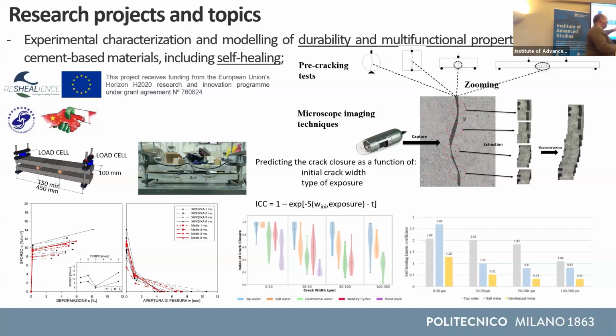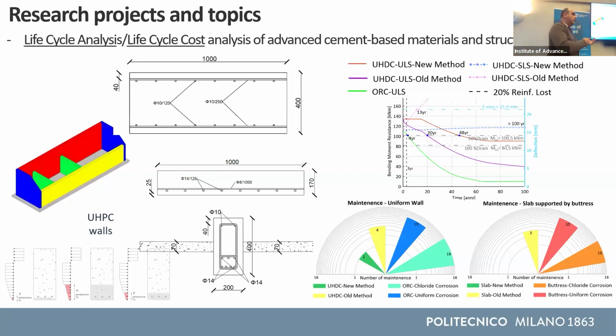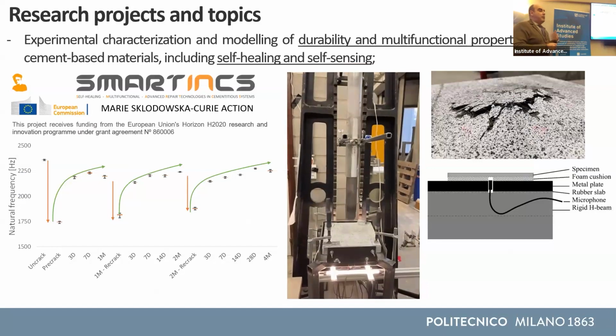So we developed a crack closure law, and we used this in the models, and we were able, through the evolution of the performance over time, to track the maintenance. So, for example, for the model for the structure with the slab supported by columns, if we used our approach, we had no maintenance or a maximum of 3 maintenance compared to 10 to 15 in ordinary reinforced concrete structure. So this was the methodology that we developed to calculate the cost. And then we went further.